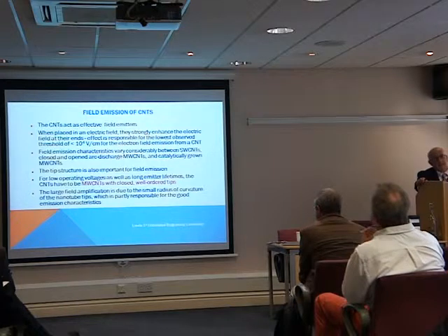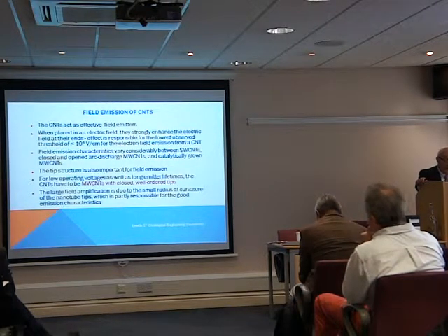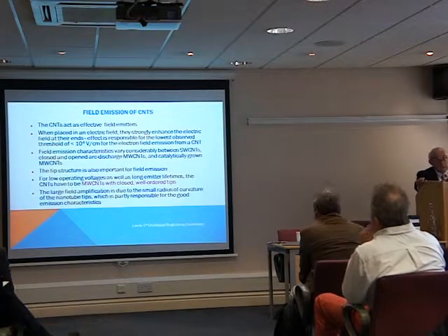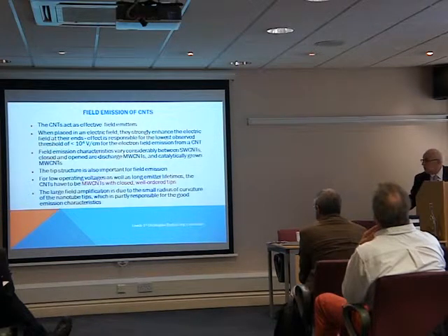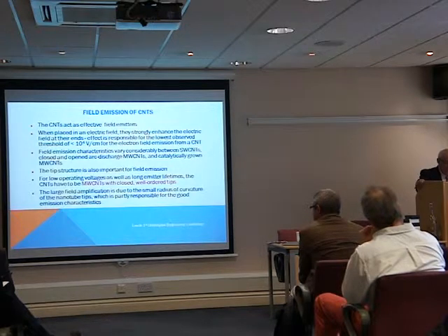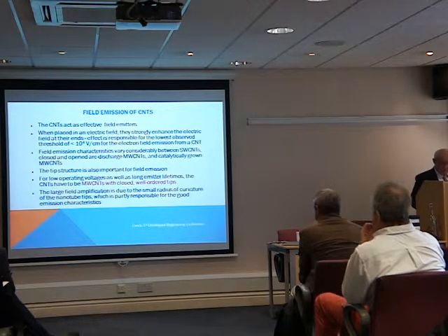Indeed, the field emission properties can vary greatly, both between single and multiple carbon nanotubes depending on their structure, and in particular their tip structure. The tip structure ideally has to be closed and well ordered. And the large field enhancement is due to the small radius of curvature of the nanotube tips.